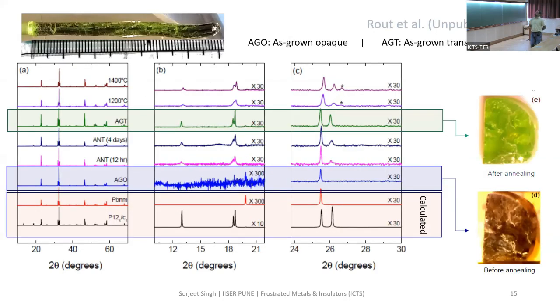So this is what we grew. This is the crystal that you get from the float zone method. And this crystal doesn't look uniform. It certainly doesn't look good because there are 2 colors. In fact, we could mechanically extract light green, translucent pieces, and then the dark pieces. So we were curious why there's a color change. Often the color change is because of oxygen off-stoichiometry. But in this case, it turned out that this color change is not because of oxygen off-stoichiometry. It is because of the change in crystal structure, which is depicted here.